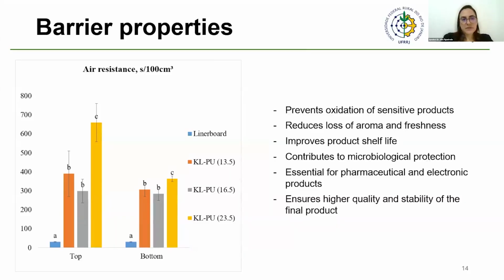So when we test the barrier properties, first we tested the air resistance, the air permeance, by the Gurley method. We see the high porosity of the paper, but the results are comparable with those reported in the literature for the type of paper we used. It was a recycled liner board paper, and the results showed 33 seconds through the Gurley method.